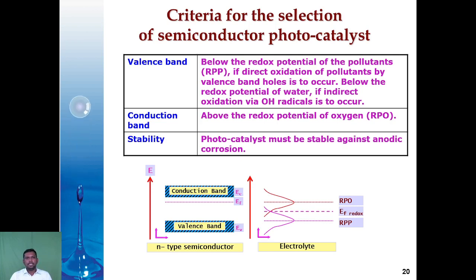So, criteria for the selection of a semiconductor photocatalyst. As I said, a semiconductor consists of a valence band and a conduction band. In the case of the valence band, the valence band always lies below the redox potential of the pollutants, if direct oxidation of pollutants by valence band holes has to occur, or below the redox potential of the water, if indirect oxidation via OH radicals has to occur. So this is the case for the valence band. In the case of the conduction band, the conduction band always lies above the redox potential of the oxygen. So this is the main condition. Let me repeat: the valence band always lies below the redox potential of the pollutants, whereas the conduction band always lies above the redox potential of the oxygen.